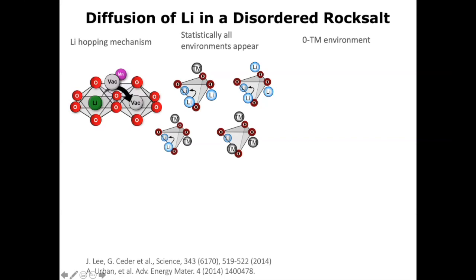And the energy of that site is set by the size of it, as well as by the metals that are nearby. You always need a diffusion vacancy. So one of these, what we call gate ions, is vacant. So the question is what the other one is. In a layered material, the fourth ion is a transition metal. And that's what you see here. And this works really well when this tetrahedron is large. And that's what Clare talked about, right?